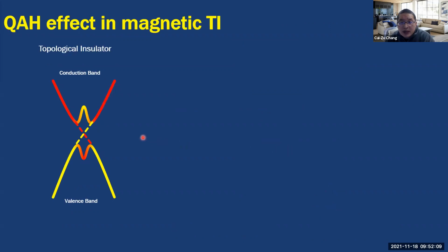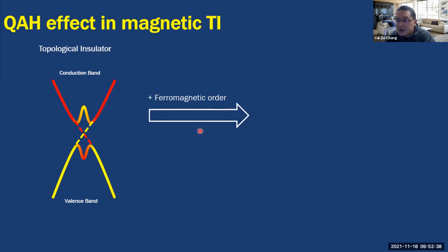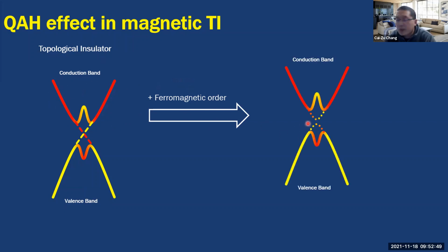As I just showed you, the topological insulator already satisfies the first condition for the realization of the quantum anomalous Hall effect. In the topological insulator, there is an inverted band structure that forms the Dirac surface state, and this Dirac surface state is protected by time reversal symmetry. So the second condition is how to introduce ferromagnetic order in the topological insulator. If we introduce ferromagnetic order, the time reversal symmetry will be broken, and a gap will open at the Dirac point. This gap we usually call the magnetic exchange gap. If we tune the chemical potential into this small gap, we could realize the quantum anomalous Hall effect.